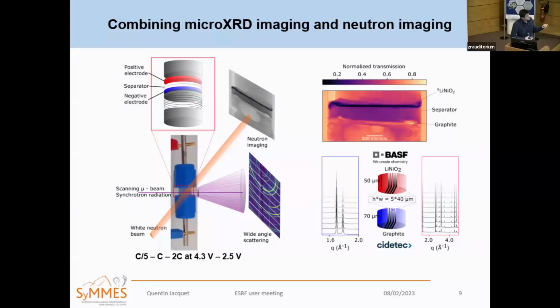To be able to correlate these techniques, you need to measure the same sample. So we basically have this Swagelok cell, which we can bring to different beamlines. Inside the cell, you have your electrochemical stack composed of commercial electrodes given by our industrial partners in the project. We first go to the ESRF, where we do micro-XRD.